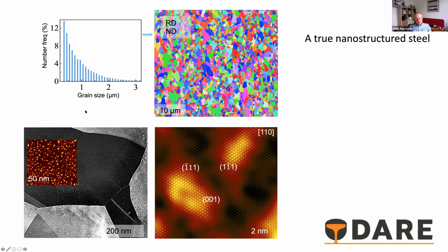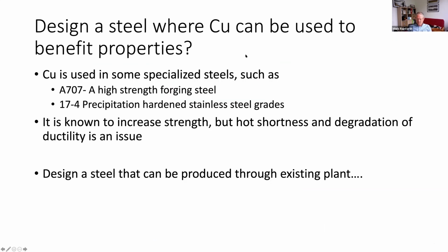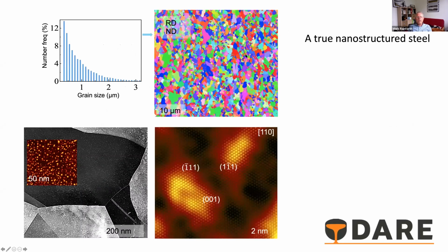Those of you familiar with steels know that commercially it is really difficult to generate grain sizes that are less than 2 microns, say, and certainly less than 1 micron becomes really challenging. But here we had a steel where we had a very large proportion of grains that were down at that very fine range. So you can see the EBSD image in the middle there, and you can see the grain size distribution there with a scale bar of 10 microns.